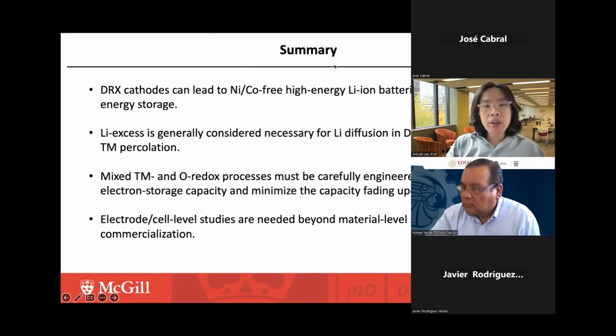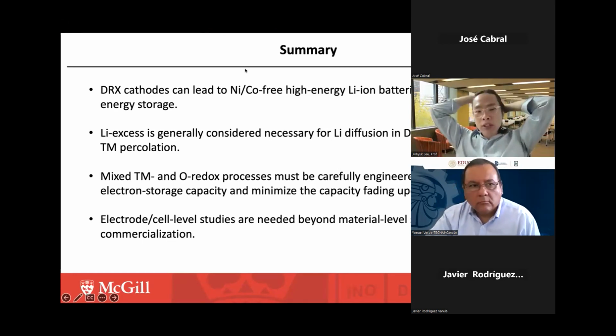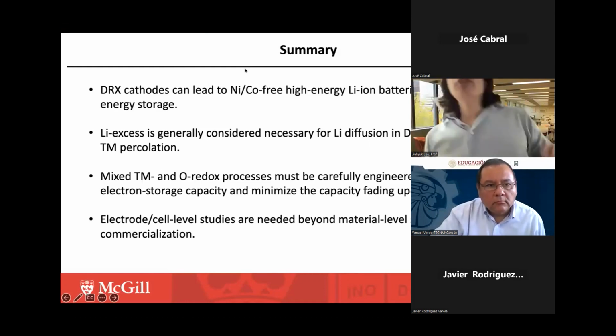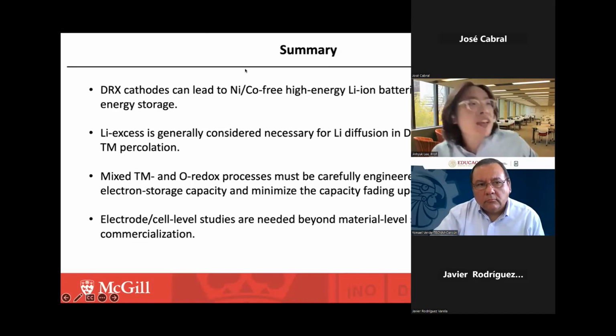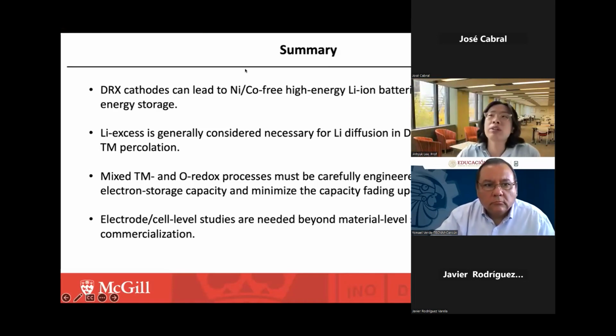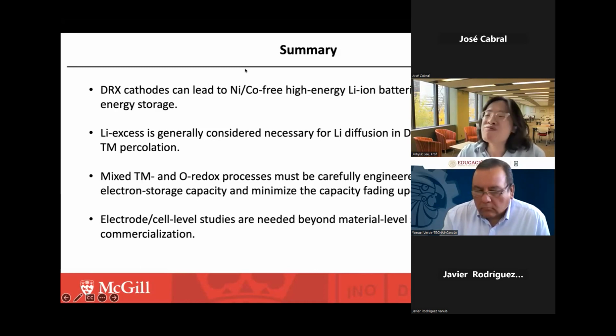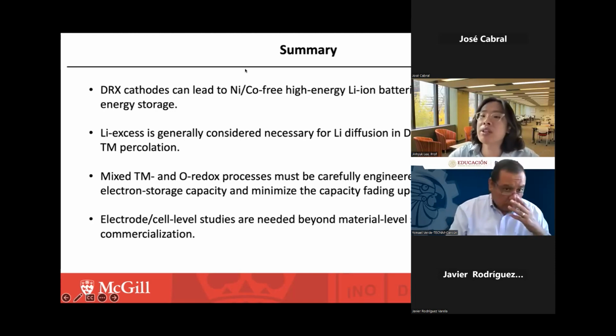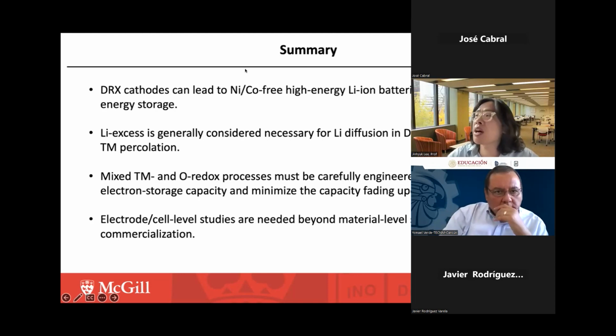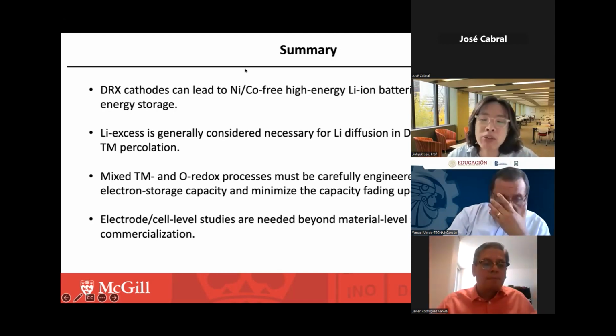Yeah, this is a very interesting, important question, and I also thought about it. When you talk about the sulfur cathode, you're talking about lithium-sulfur batteries. When you talk about large-scale production or the fate of the battery technology, you have to see it at the cell level, not just the cathode level. In theory, a sulfur-based cathode will outperform all the available cathode materials. But to operate the sulfur cathode, people typically use a lithium metal anode, right? And assuming some level of thickness, people have predicted that the gravimetric energy density of the lithium-sulfur battery can be greater than the lithium-ion battery's gravimetric energy density.